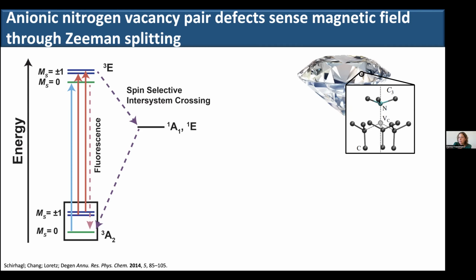You can take ions and bombard a diamond with them and create a scatter shot of defects. One of those defects that you can create is the anionic nitrogen vacancy pair defect in diamond. And there you have a chemically insane species, which is buried deep within the diamond. And I say chemically insane because you have an S=1 sp3 center, fundamentally. Now, this is something that I find personally upsetting, but that's what it is.